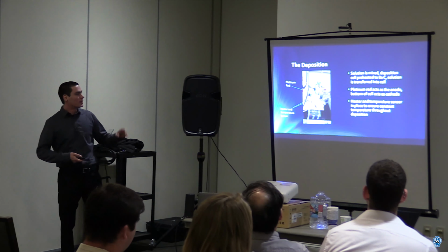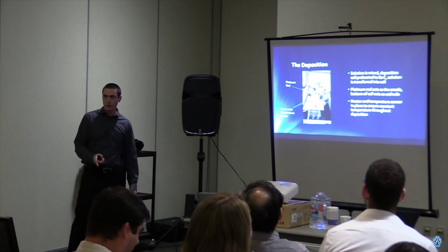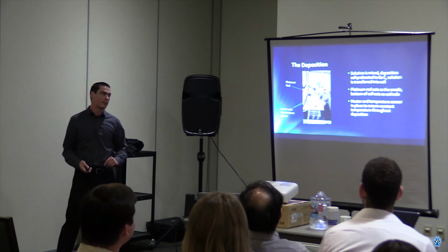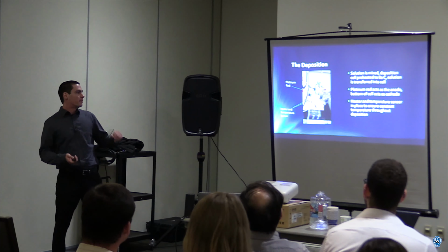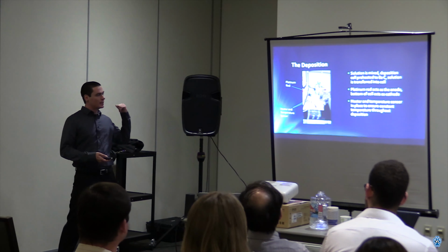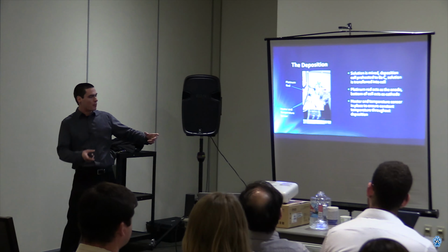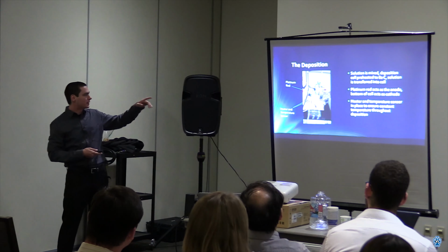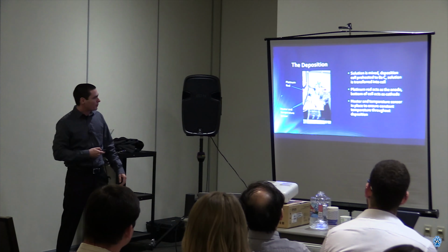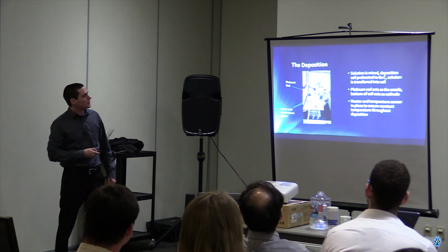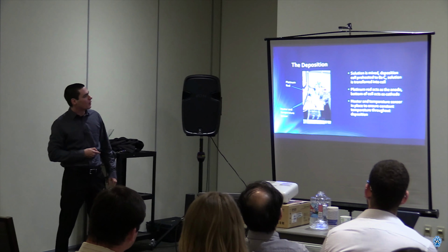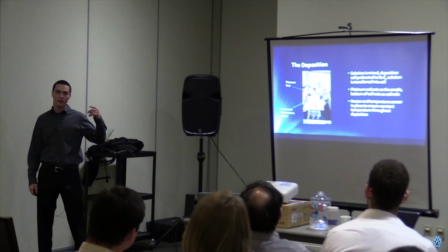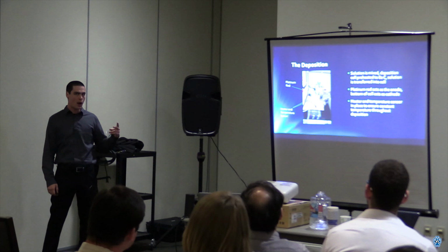And then once that gets to temperature, once my solution has been mixed and is now, ideally, completely transparent, basically I can empty out what's in the container here and then pour my solution in with a little magnetic pill that stirs, and I can connect the circuit using a platinum rod that is inserted into the top of the deposition cell. And the platinum rod is connected to the positive terminal of a 3 volt power supply.